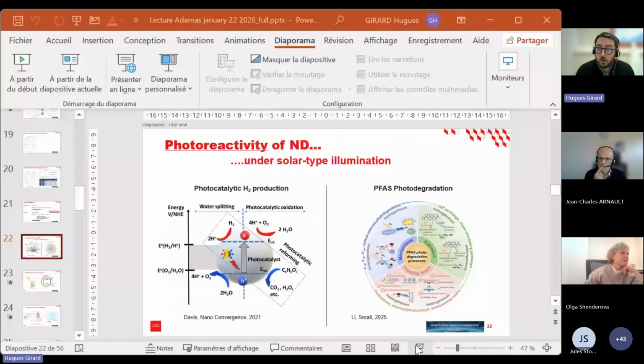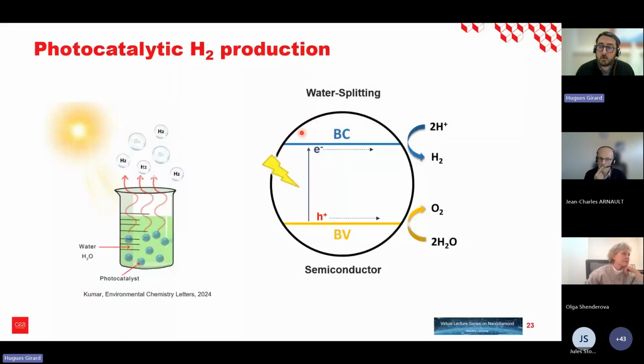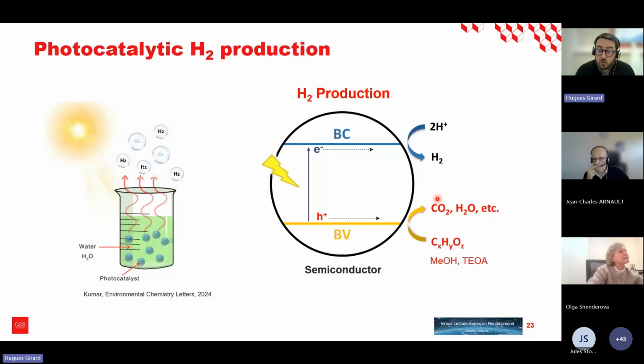But in our case, due to the design of the photoreactor that we can use, we want to avoid the production of the oxygen. So what people usually do when you want to make photocatalytic hydrogen production is use a sacrificial reagent which will consume all the holes which are produced at the valence band. And for instance, you can use an alcohol.